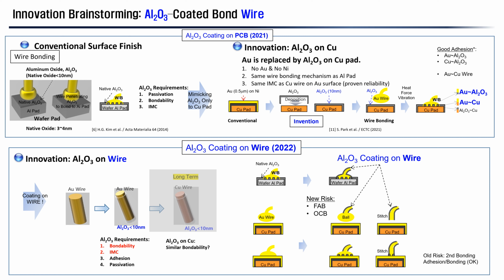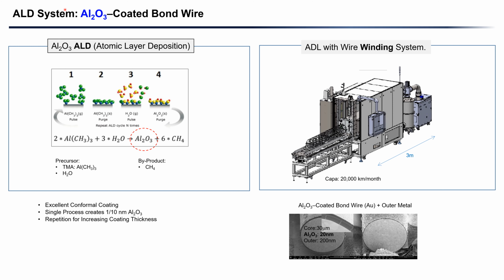Aluminum oxide was coated on a bond wire by making use of ALD, atomic layer deposition, because ALD is very well known for excellent conformal coating. Precursor for the ALD deposition is trimethyl aluminum, and H2O is a reactant. And as a result, you get aluminum oxide deposition. Byproduct is CH4. A single process creates about 1/10 of 1 nanometer. So you have to repeat the same process as many times as you want until you achieve desired thickness of aluminum oxide.